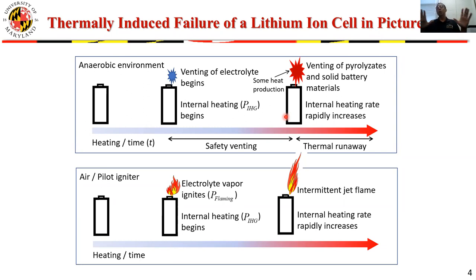Now that heat, this reaction will quickly accelerate. The cell can become red hot within seconds. Usually it can easily reach temperatures of 700 to 800 degrees C. And at that point, you will also have a significant increase in the ejection rate of the battery materials. So this is what happens in an anaerobic environment.